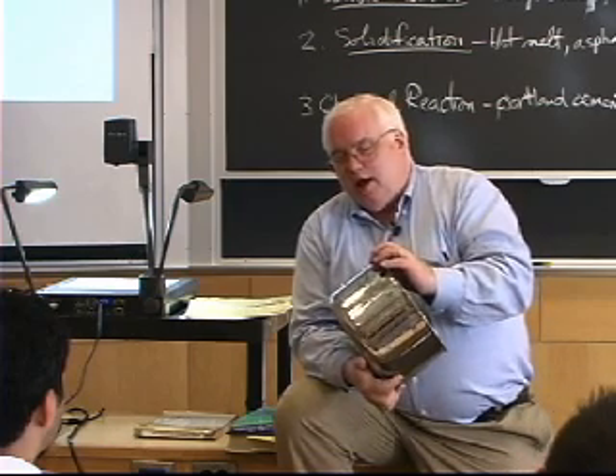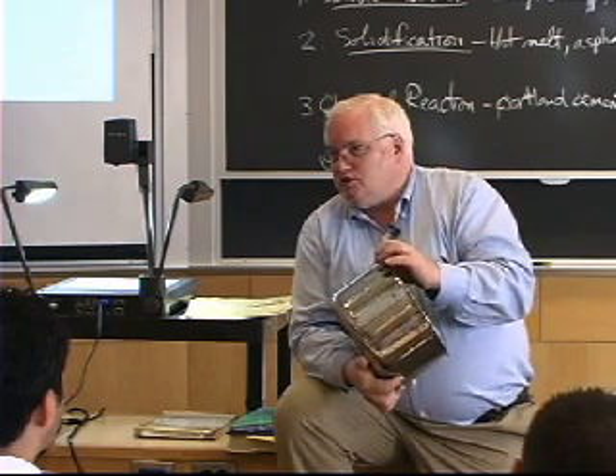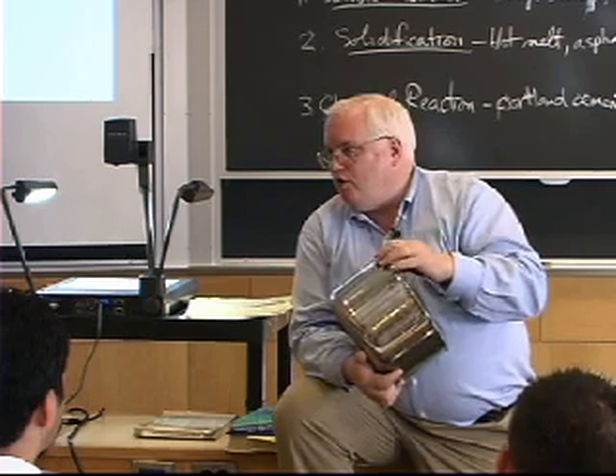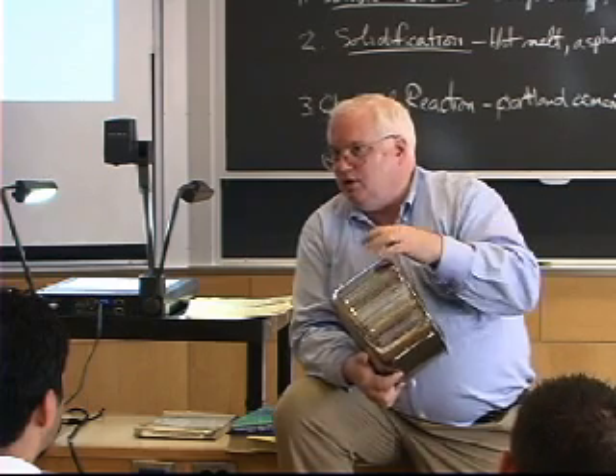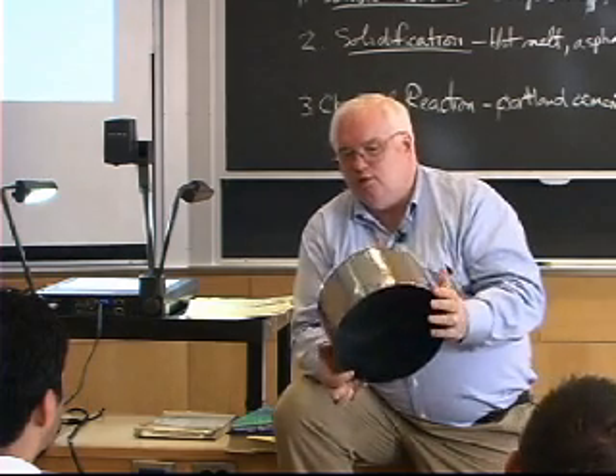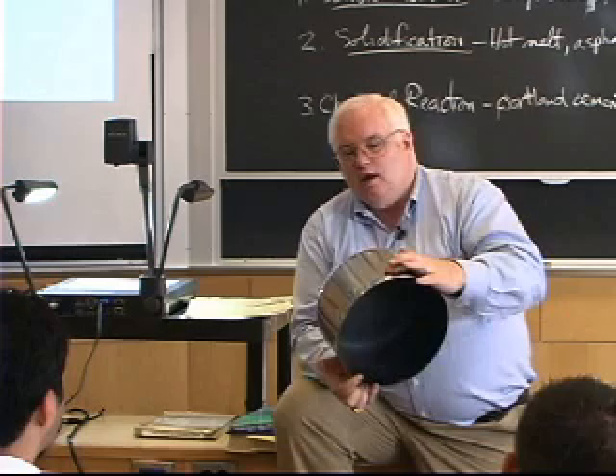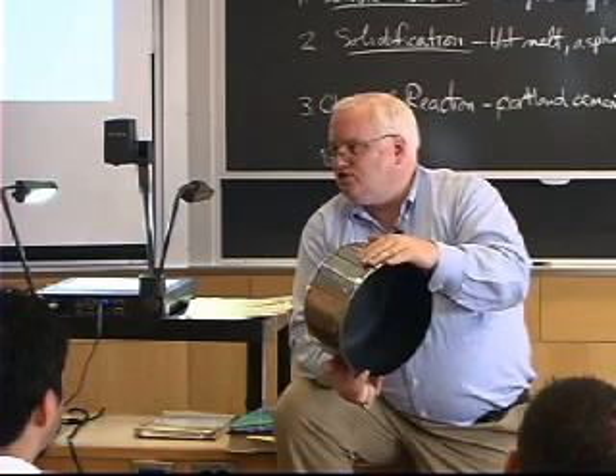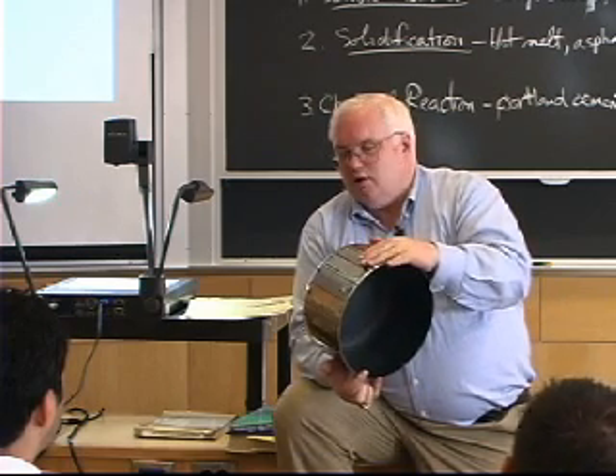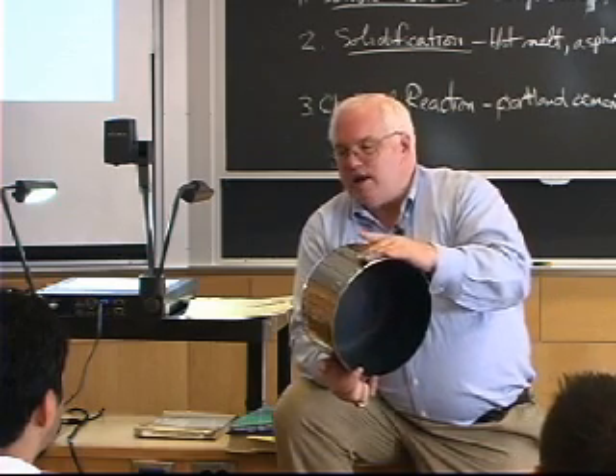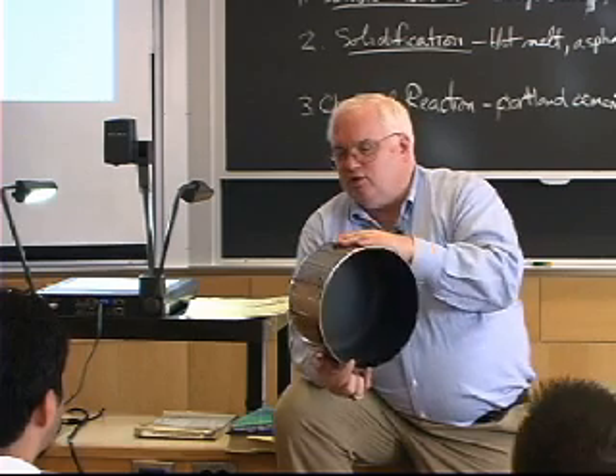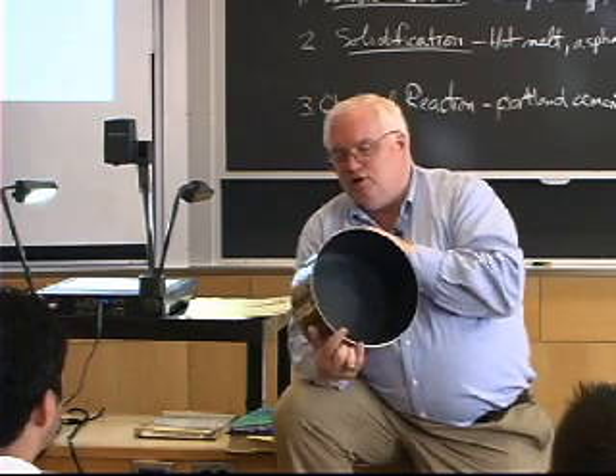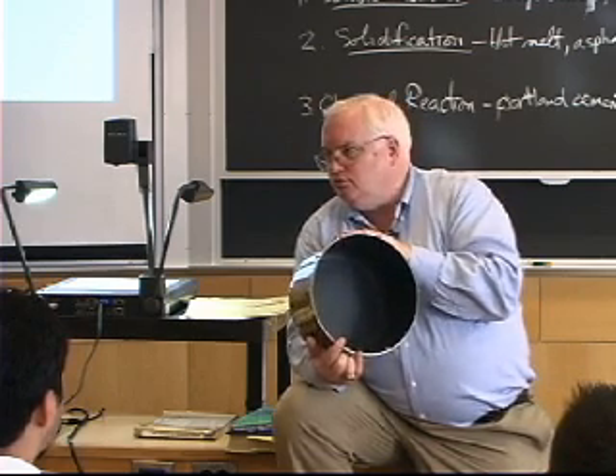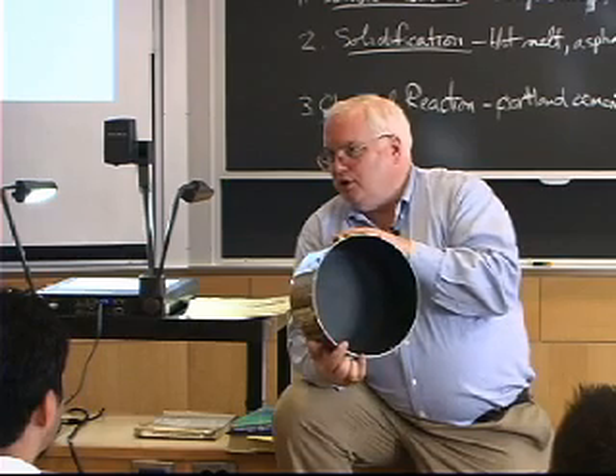But then you have to have a source of stress. What's the source of stress here? Well, the whole thing was formed from a sheet and into a deep draw here, and that creates some residual stresses, particularly up here. However, that's not the real reason, because the 300 series stainless steel is face-centered cubic, which is generally fairly immune to hydrogen embrittlement.